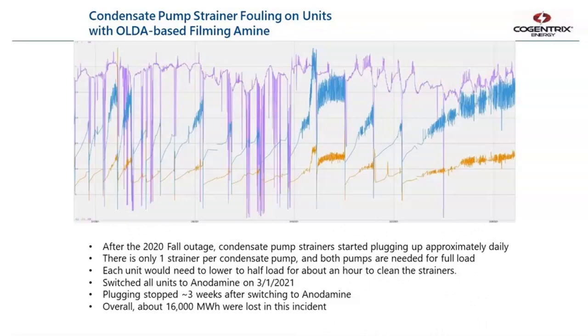So here's a picture of the gunk ball incident. A lot of the purple lines you see there are the plant load, and the orange and blue lines are the condensate strainer differential pressure. And what happened is when we started up after that outage where we had the gunk balls, we experienced the condensate strainers plugging up. This plant has 2 50% condensate pumps, and they each have a simplex strainer, so there was no redundancy to be able to change them. And then you could see every day we were having to come down on load and change the condensate pump strainers, and that went on for about 2 months.